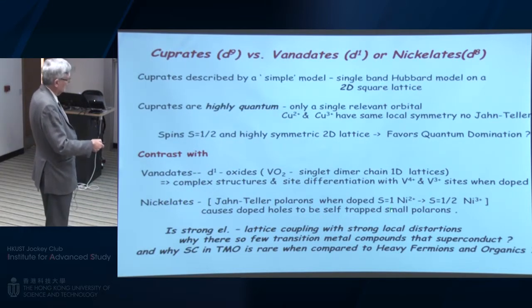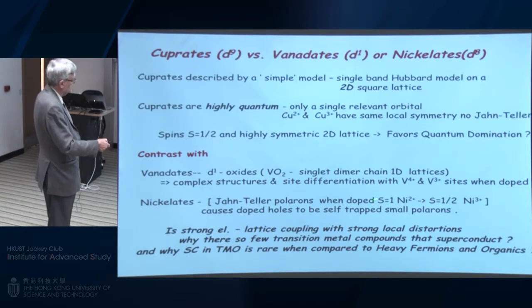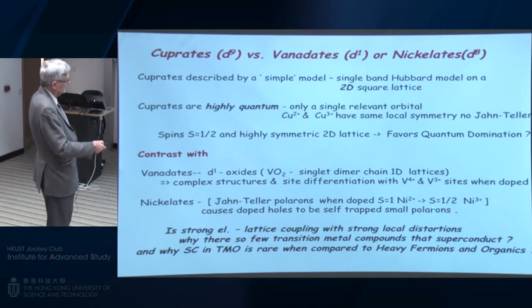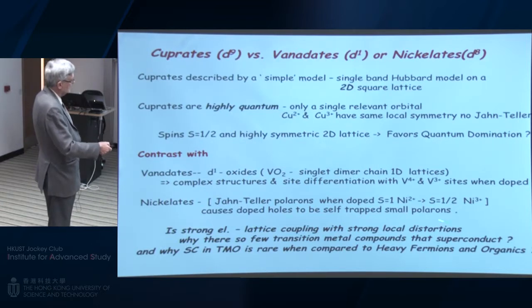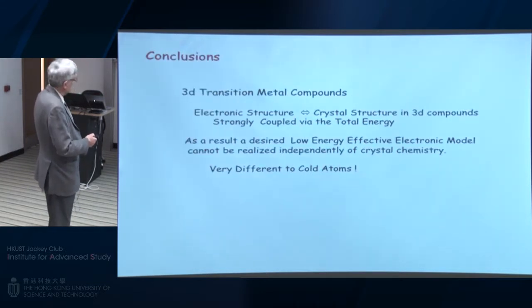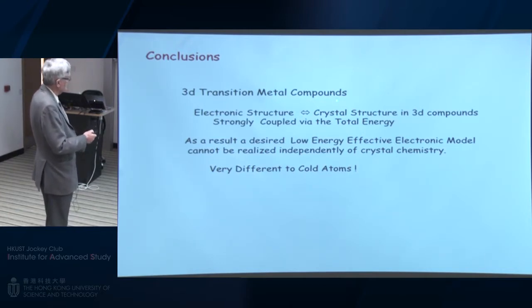And it has at half filling an S equal 1 nickel 2+. So that's the state we don't have in the cuprates. It's this S equal 1. So then if you take an electron out of nickel, you get a Jahn-Teller effect. You get a big distortion of the octahedra, which self-traps this polaron so it doesn't move freely. So these materials just behave very differently. So the conclusion is if we are looking at 3d transition metal compounds, their higher bandwidth, which we were using to get higher Tc, however, introduces an unwanted complication, namely their electronic structure is related to the crystal structure that they form.